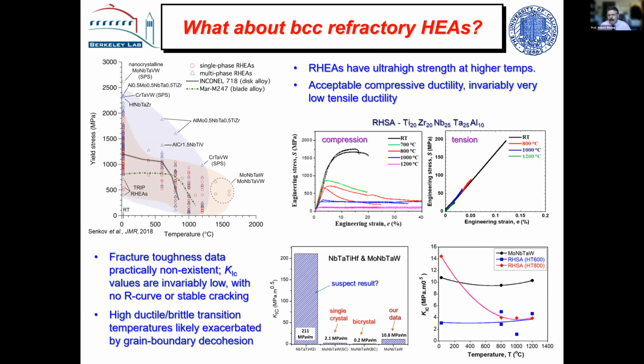The problem is that most people have studied these in compression, which gives a false sense of security. These are the different alloys, titanium, zirconium, niobium, tantalum, aluminum. This is the test we did in compression. Look at the engineering strains here, up to 40%. If we do them in tension, look at the engineering strains, 0.15%. And it breaks nowhere near the yield strength. So these materials have very low tensile ductility, and they have a very high